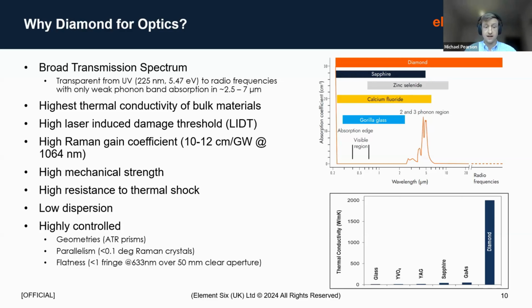Also of interest, perhaps less for laser windows, is high resistance to thermal shock, in situations where there might be a sudden high heat load on a window. So for example, you could use diamond for a missile dome. If that gets very hot very suddenly, diamond is unlikely to fracture as a consequence of thermal shock, because the thermal conductivity is so high in the diamond.